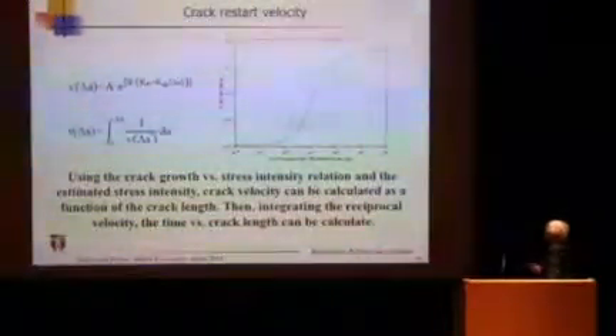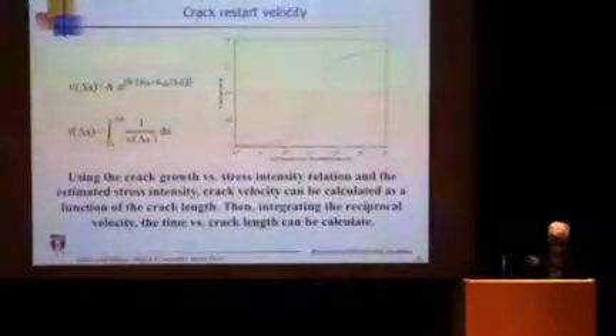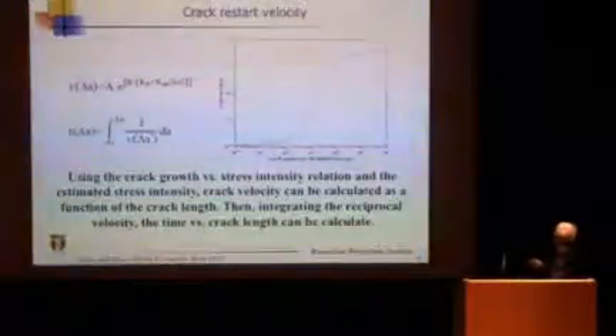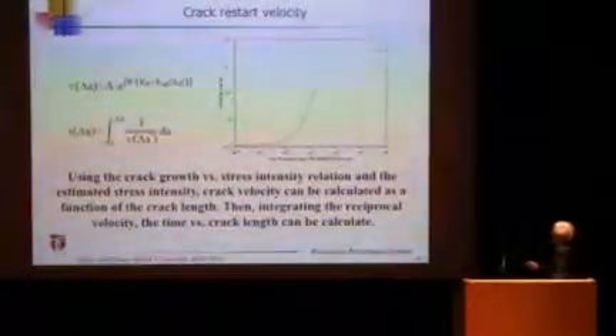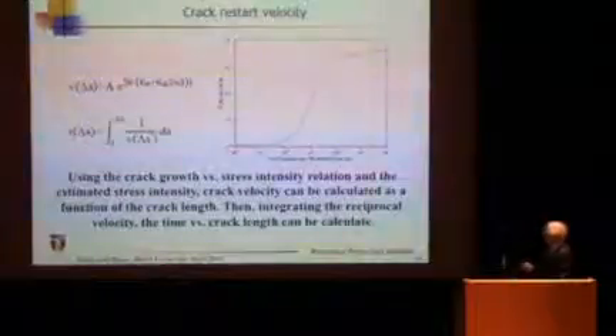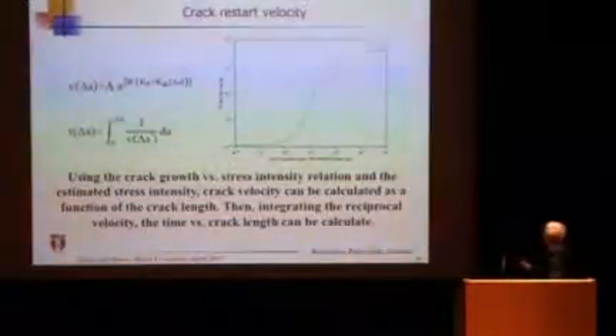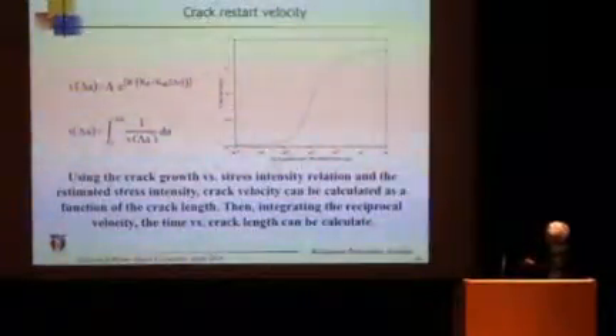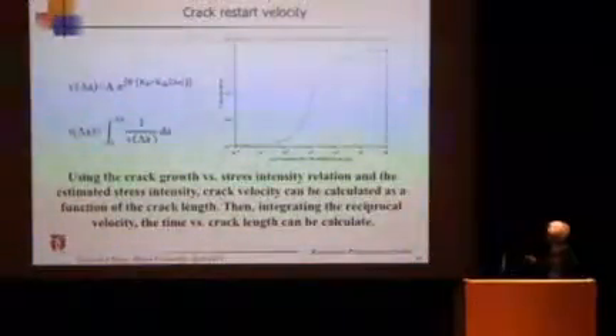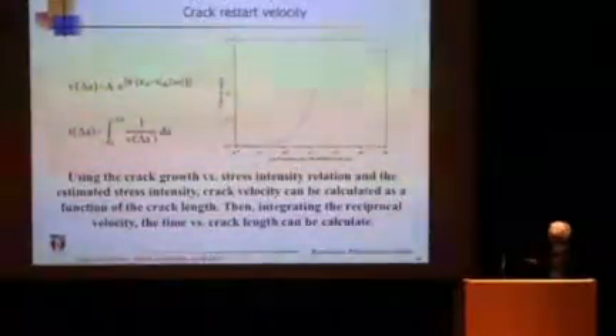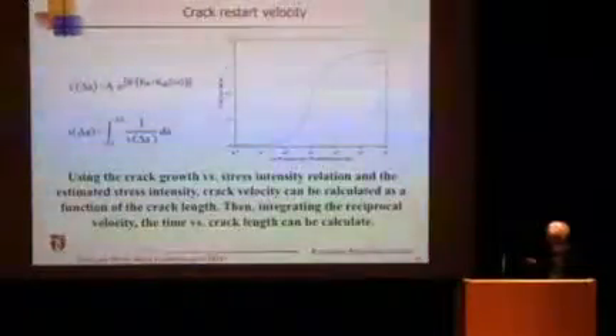So the velocity of the crack, we assume that the original crack growth line stays linear, ideal case, if there is no shielding. But we have to introduce shielding, and therefore it will take time to propagate in this region where there's shielding stress intensity. So crack growth is very small.